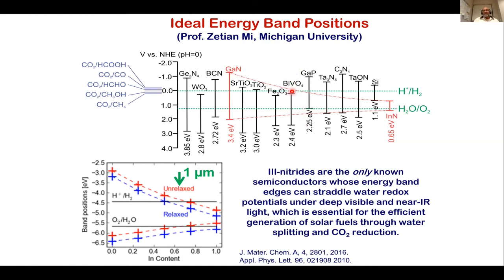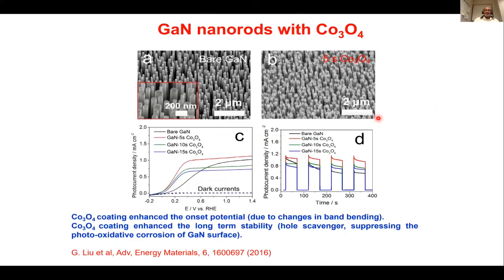But if you make indium gallium nitride, a combination of indium, gallium and nitrogen, then you get a band gap which can absorb visible light and also straddle the redox potentials somewhat. So in that direction, we have been looking at gallium nitride nanorods, and this is the work of my colleagues from engineering and also from my group in physics.